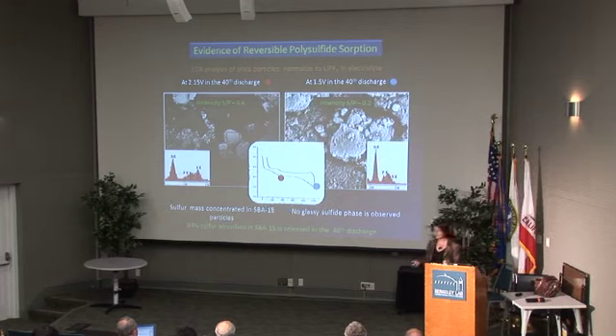And we didn't do this, obviously, for one particle. We did them for 100 particles and averaged. And what we learn is that 94% of the sulfur that's absorbed at this point is actually released on full discharge. And the other thing you'll notice here is that there are no glassy sulfide particles whatsoever, even after 40 cycles.